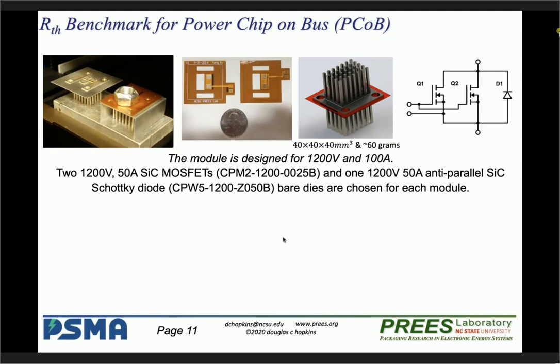What he showed here takes the heat sink at the top would be electrically hot, sitting on, let's say, the source gate side. The bottom heat sink sits on the drain side. It's coupled together directly in contact with the die with a mechanical buffer. He used a Moly tab to do one side of stress management. And then also in the center of it for the gate drive, he implanted a flex circuit to be able to pick up the gate interconnects.